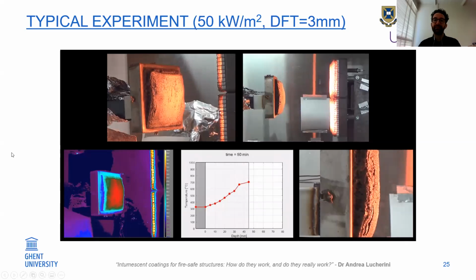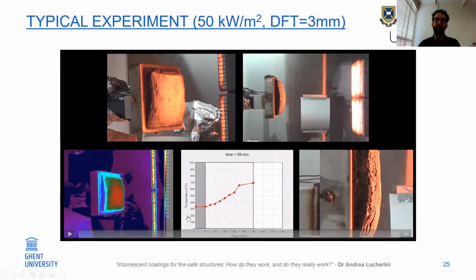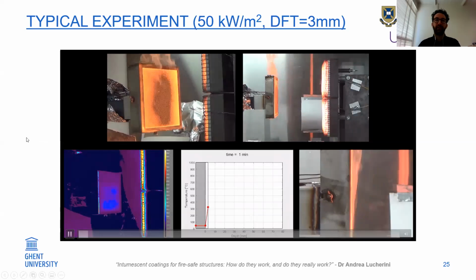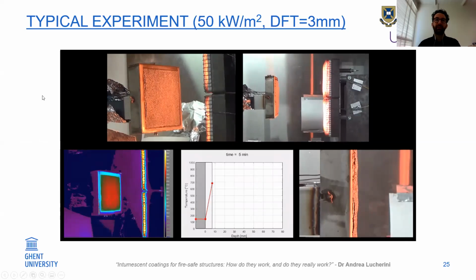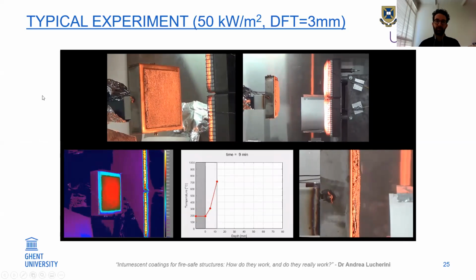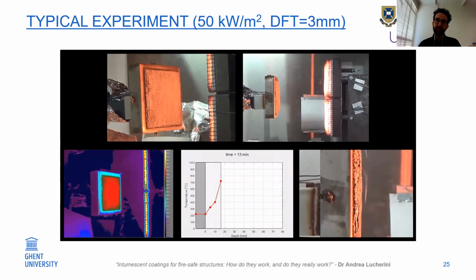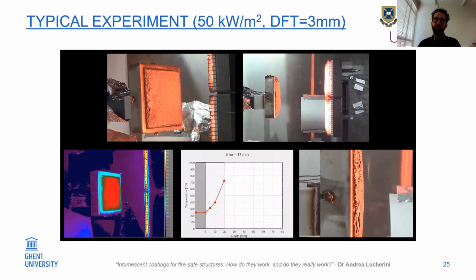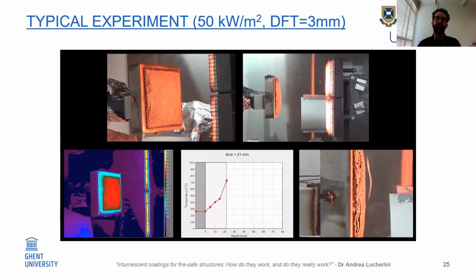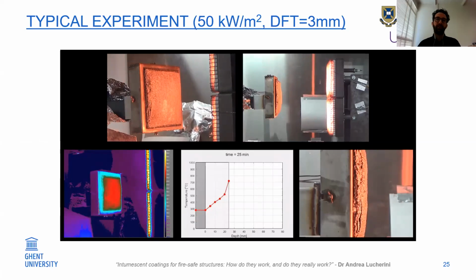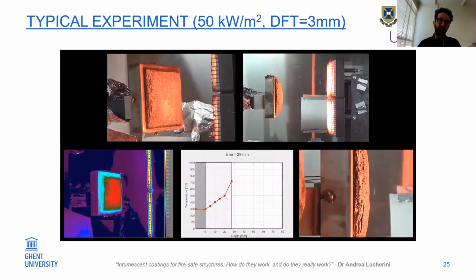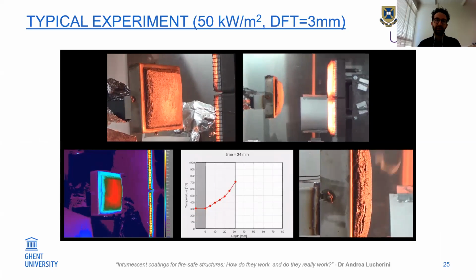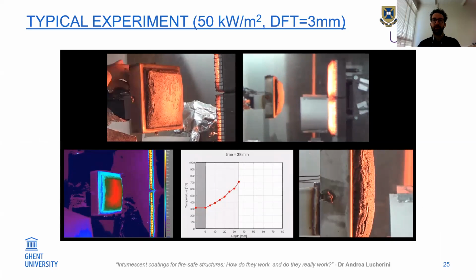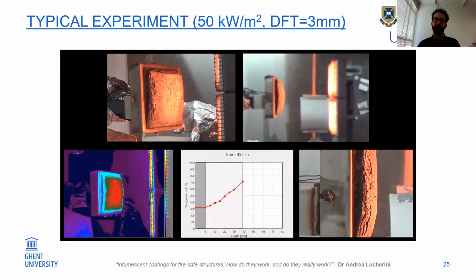And what you can mainly see is the swelling of the Intumescent coatings. What is interesting, maybe you're wondering why the radiant panel, while the coating is swelling, is moving backwards. What I was trying to do was apply a constant incident heat flux at the exposed surface. Therefore, if the coating swelled during the test, the surface was getting closer to the radiant panel, so the incident heat flux would increase.